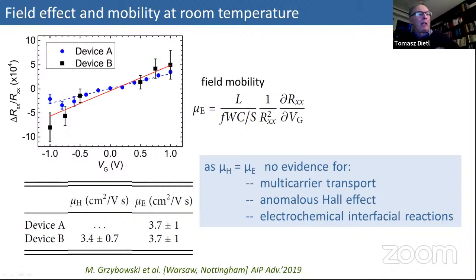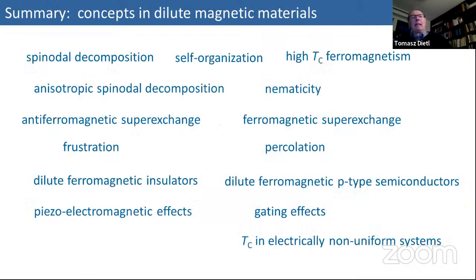So this brings me to the end of my talk. Just to summarize, I have introduced, or reminded you of, several concepts in dilute magnetic materials: spinodal decomposition, which leads to self-organization and may lead to high TC ferromagnetism in some cases. Also, anisotropic spinodal decomposition is a very interesting effect, which leads to nematicity in many systems. I contrasted antiferromagnetic superexchange with ferromagnetic superexchange, saying that this leads to frustration and spin-glass freezing, but here we have percolation, a very nice test of percolation theory.